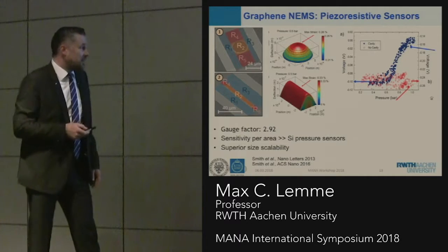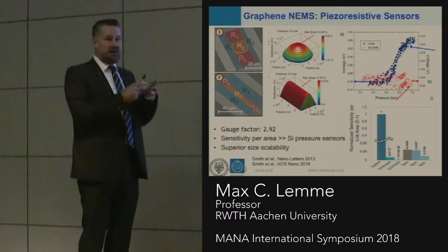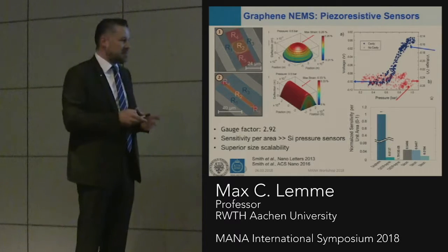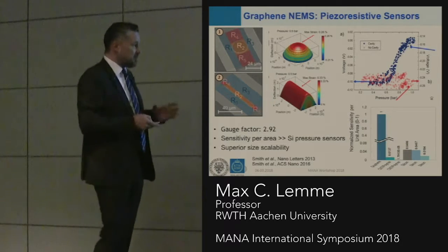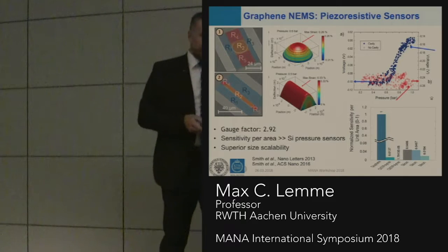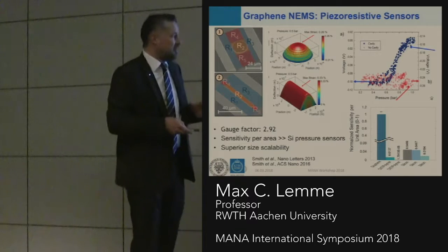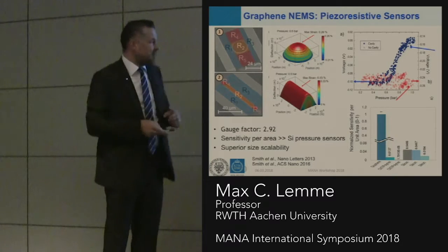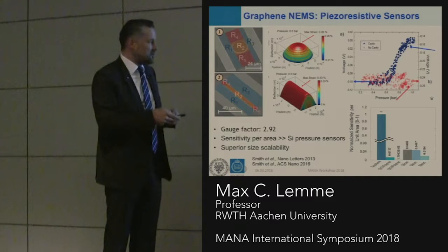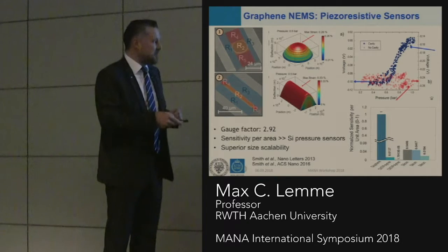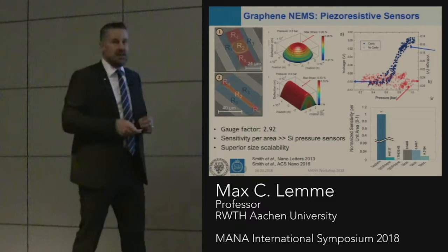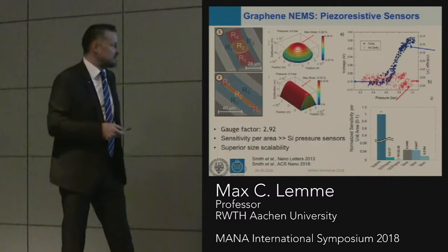We also calibrated this to the size of the device and compared it with state-of-the-art technologies. Because the membrane is so thin, we actually get very high sensitivity per unit area. You can see here the graphene is normalized to 1, and then we get 5% or less for existing technologies with this normalized sensitivity.